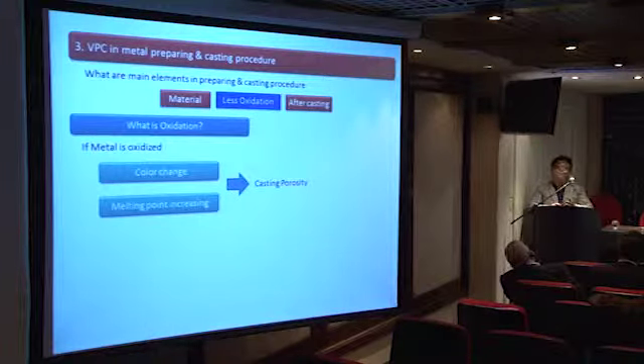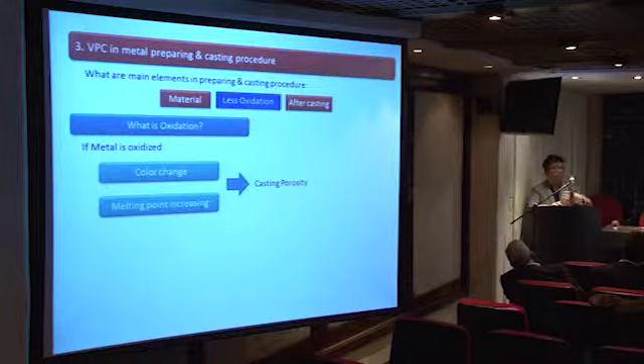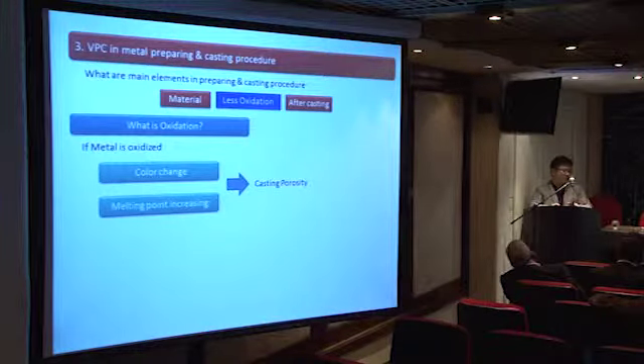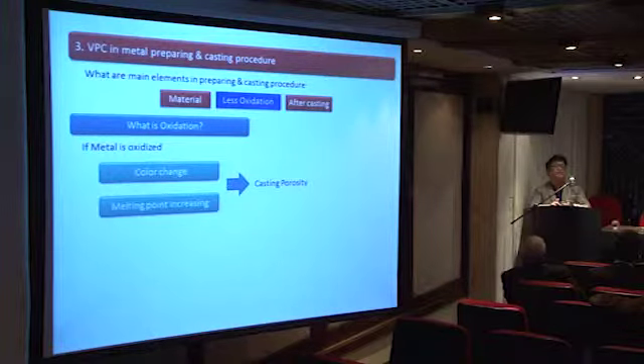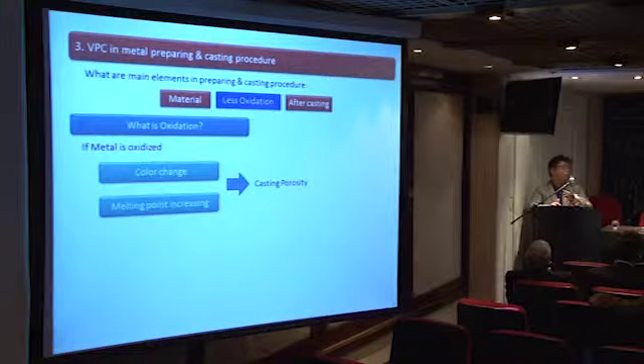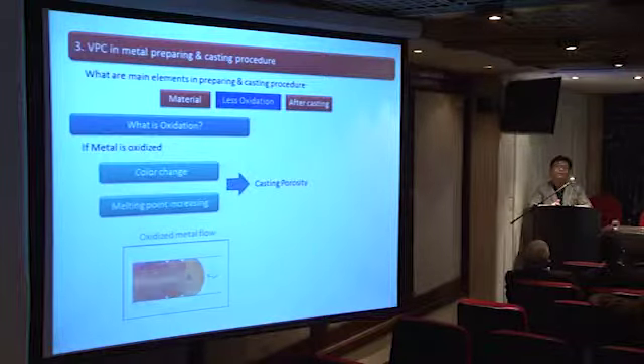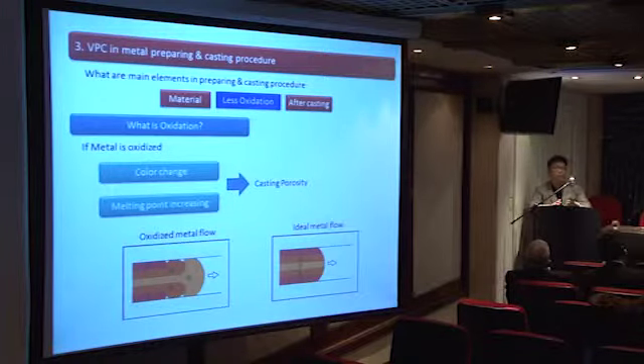If you have oxidation, the melting point increases. What it means is, if your melting point is lower, in terms of casting, the lower temperature makes a better casting or smoother surface. So if you have an oxidated metal, the metal temperature simply increases, where you have to cast at a higher temperature, where you have more risk against your metal. So basically, you can consider that you'll have more problems with an oxidated metal than casting with a non-oxidated metal.